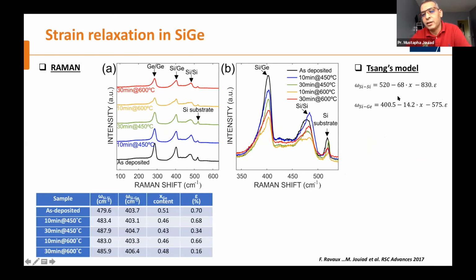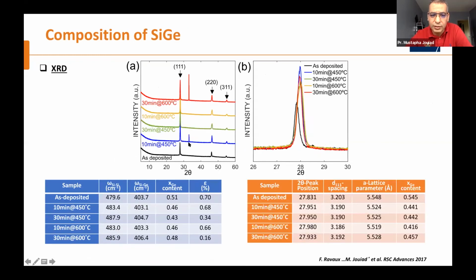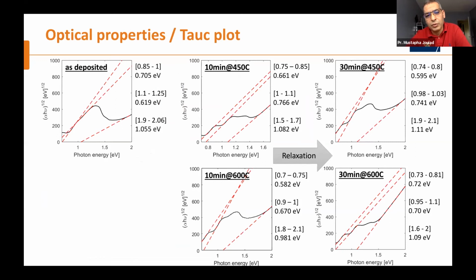And by using the Tsang's model, we were able to obtain the stress release and also the composition of silicon germanium. You have the content down here. This is Raman shift, and we did the same thing with XRD, and we obtained exactly the same composition. You have the composition percentage of germanium in our silicon germanium compound, and they are always similar. This led us to different compositions, and we measured the band gap for each composition. Starting from as-deposited and doing different heat treatments with the relaxation, we can obtain band gaps from 0.6 to 1.09, which actually covers a very large known band gap range of silicon germanium. This is very interesting.